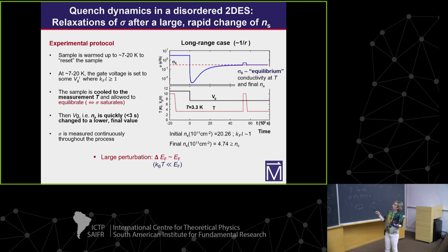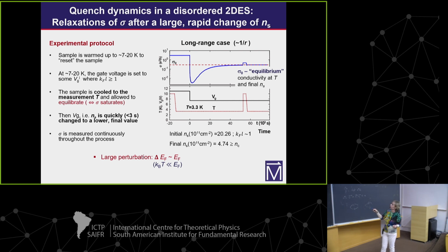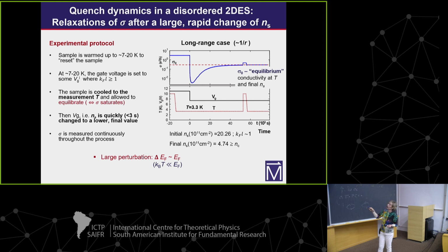And then we monitor the evolution of the conductivity with time. This is shown here at the top. First I'm discussing this case of the long-range Coulomb interaction. You can see conductivity drops quickly when we change the total density quickly, but then it takes a really long time—many hours here—for it to reach some kind of a steady state.